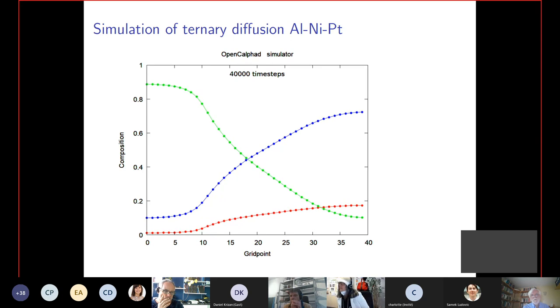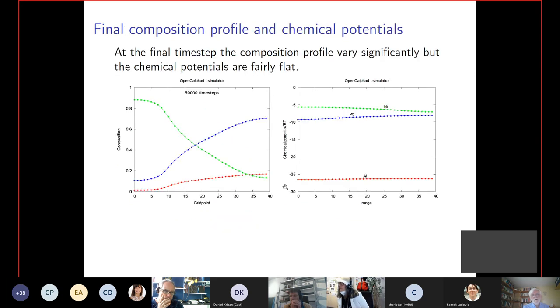This is what is happening with the time. I stopped at 50,000 time steps, and you can see the chemical potentials at the end. Aluminium is almost horizontal, but you still have a gradient in composition because the aluminium chemical potential is affected by the nickel and platinum.